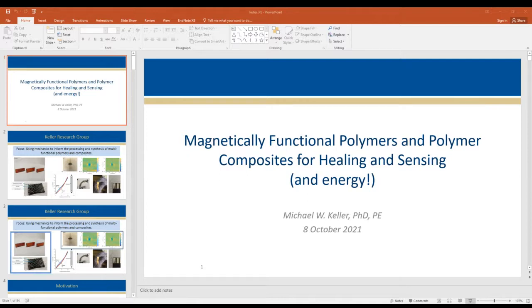And what you have here is an ultrasound measurement, and this is visually taking a picture. So this is it undamaged, this is the material injected, this is the ultrasound, and so you can see this dark region that represents the damage that was prior to us injecting it. This is our thermal image, and then this is a magnetic scanning image. And this magnetic scanning image is a little messy, but this is sort of magnetic flux measurements that we do.